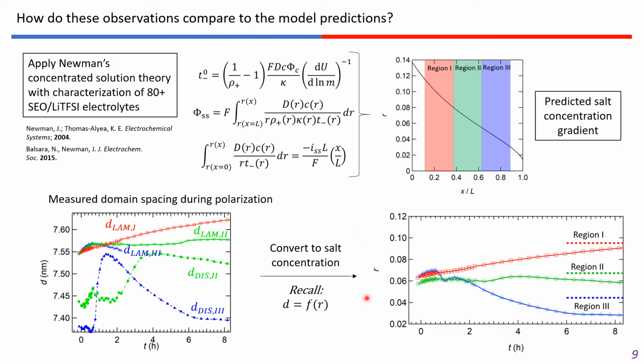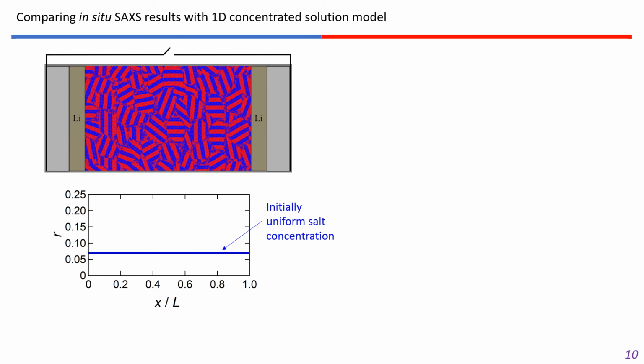And that is what I'm showing here: the experimentally measured local salt concentration as a function of time. And we see that we have fairly good agreement, where the solid lines represent the experimental data and the dashed lines represent the theory predicted at steady state. And we obtain fairly reasonable agreement to at least confirm the magnitude of the predicted salt concentration gradient. So we're now able to compare our experimental results to the theory.